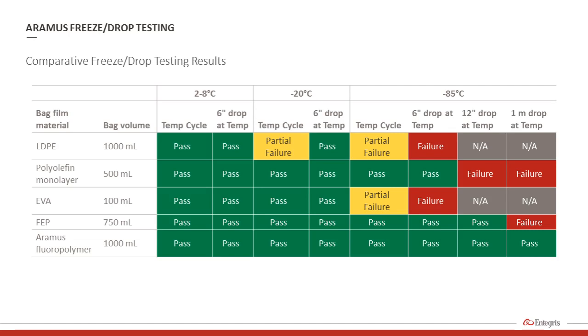Materials tested including polyethylene, polyolefin, EVA, FEP, and the Aramus fluoropolymer. This table shows the results of the testing. All the bags passed at the 2 to 8 degrees C range. So they passed the temperature cycle and they passed a 6-inch drop test.